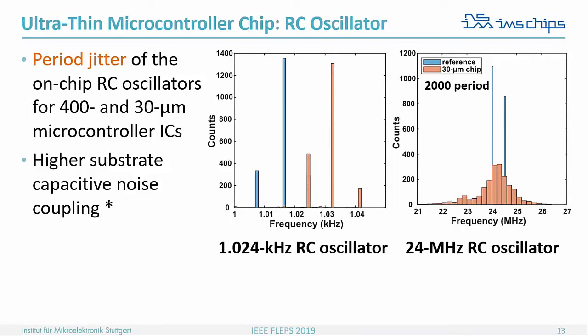The final test that we have done is on the RC oscillators. So there are two oscillators on this microcontroller, low frequency and high frequency oscillator. And you can see that there is a static offset in the low frequency oscillator. There is a histogram test for the period jitter of the low frequency oscillator. However, this offset for the thinned chips could be trimmed. So that offset we can compensate.